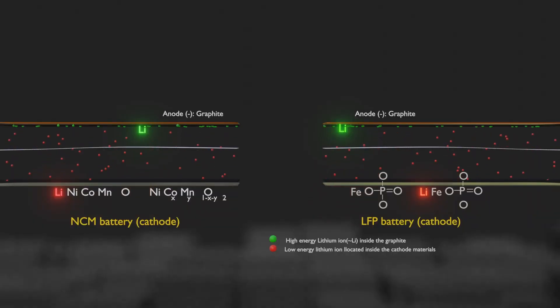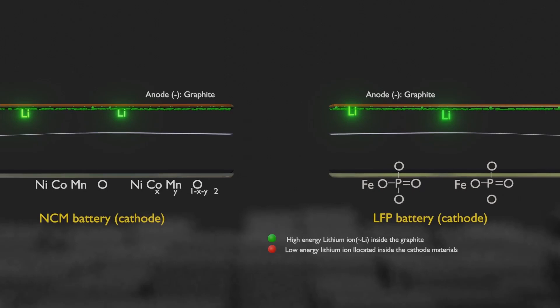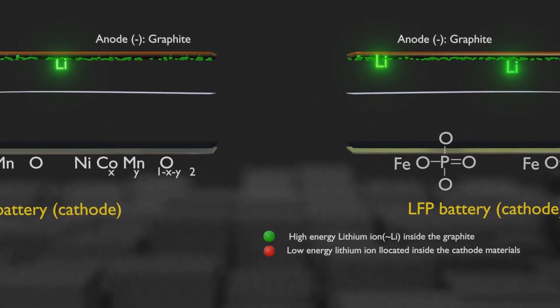What does a cathode material that stores low-energy lithium have to do with stability? The reason lies in the composition. NCM and NCA cathode materials are mainly composed of metal oxides — a combination of metal and oxygen. On the other hand, LFP is a chemical compound where oxygen atoms are part of a phosphate molecule rather than a direct chemical combination with iron. This difference becomes more pronounced at high temperatures: when an NCM or NCA-based material in a charged state is heated, it begins to decompose at around 200°C and generates oxygen. LFP cathode material, on the other hand, produces very little gas.